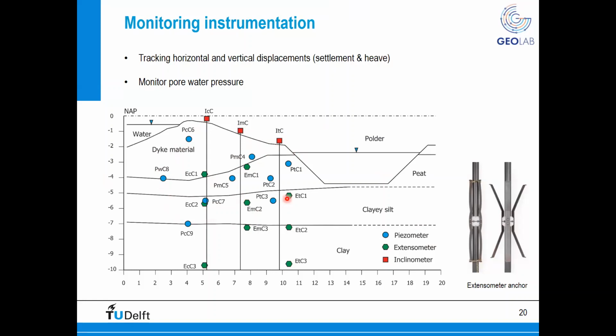But also, and it's quite important, we also installed extensometers. The extensometers were basically anchors that we placed at the interface between the different layers, so between the bottom of the dike and the top of the clay silt, and so on, in such a way that we were able to reconstruct not only the horizontal displacement, but also the vertical displacement on the different layers. And we will see later on why this information was quite useful for us in understanding the behavior of these